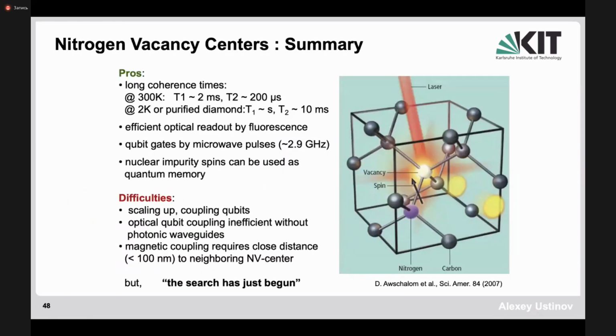So my summary about these impurity states in nitrogen is on this slide. The advantage is that coherence times, even at room temperature, are appreciably long. It's very efficient and convenient to read out these states by fluorescence, manipulate them by microwaves, prepared by laser pulses. However, to make the coherence really significant for doing quantum computing, one needs to remove unwanted isotopes, to remove unwanted impurity spins. At the same time, one can use these impurity spins as quantum memory, which is also an advantage, but it still remains to be seen if it really works.